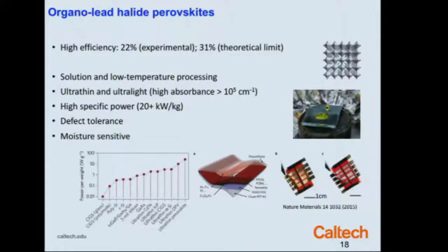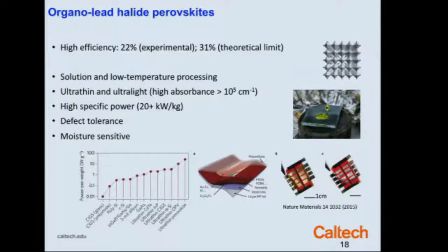These materials are remarkable photovoltaic materials. They are seemingly immune to defects. In polycrystalline films, they have performance that rivals the gallium arsenide in terms of the luminescence and the voltage performance. I showed that in some of the slides on Tuesday. They are very highly absorbing. You can spin coat them as thin films. You can doctor blade them. You can spray coat them onto polymers.